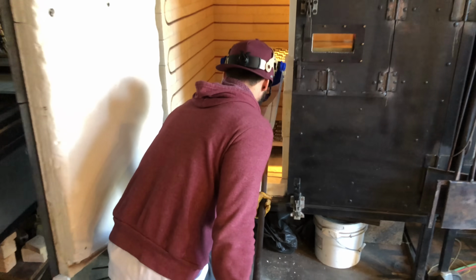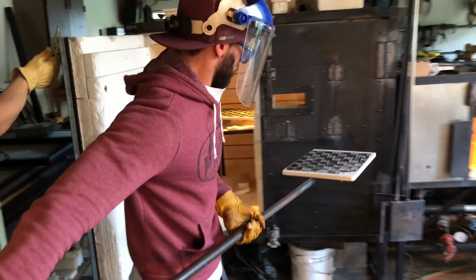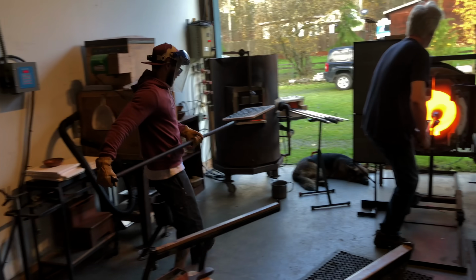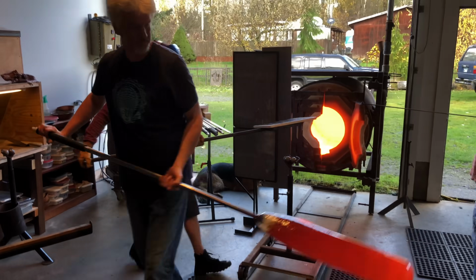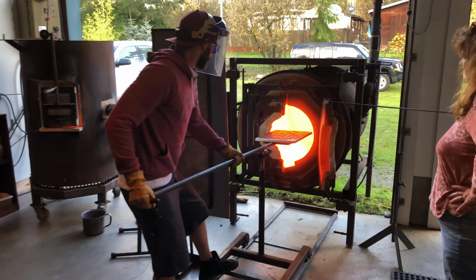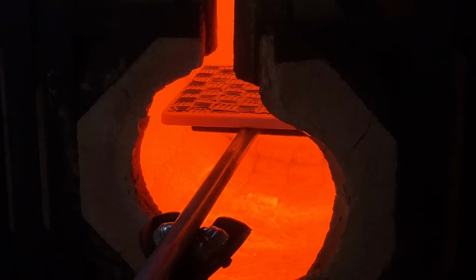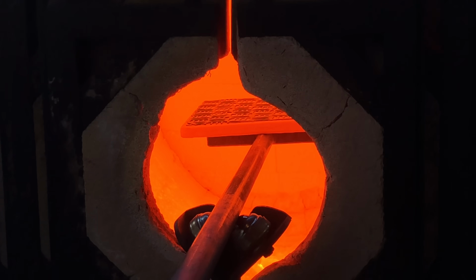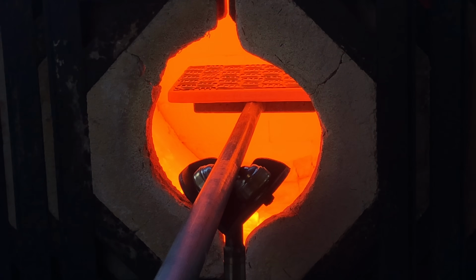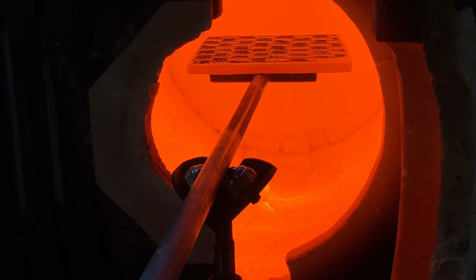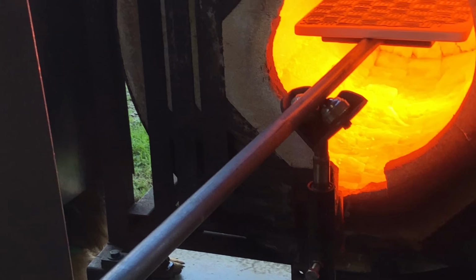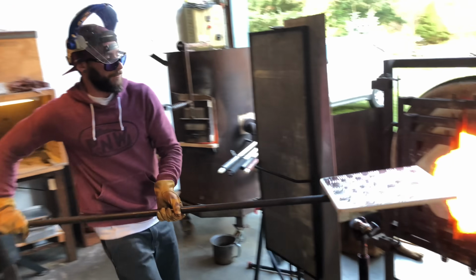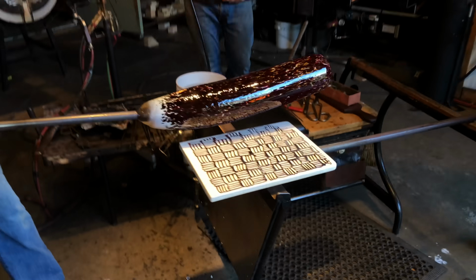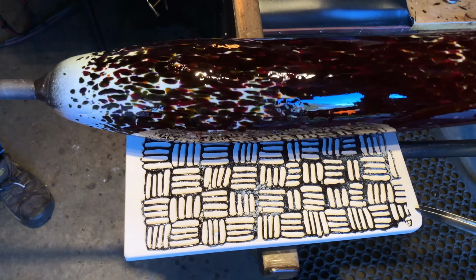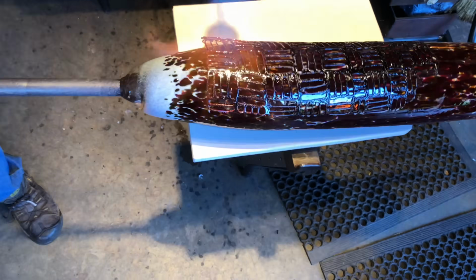Chris goes in with the forks to grab the first sheet of kiln shelf. The fusing came out of the kiln at about 1050 degrees Fahrenheit. And now Chris is heating it up so that it can bend at about 2300 degrees Fahrenheit. That looks good. Coming out. They only have one chance to stick the glass on so that it's soft enough to wrap onto the outside of the bubble.